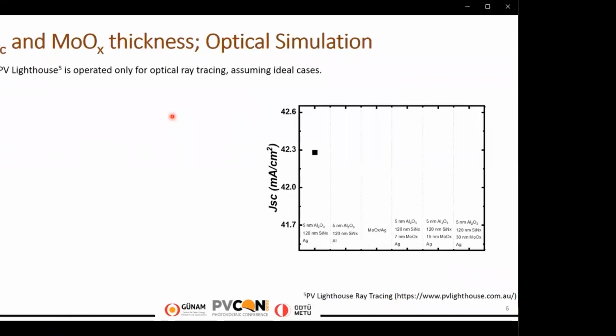But first, in order to find the molybdenum oxide thickness and JSC correlation, PV Lighthouse is operated for optical ray tracing, and it assumes ideal cases at the interfaces and does not take into account electrical resistance losses, passivation losses, etc. And it assumes an ideal emitter. First, a 5 nanometer aluminum oxide and 120 nanometer silicon nitride silver stack is utilized.